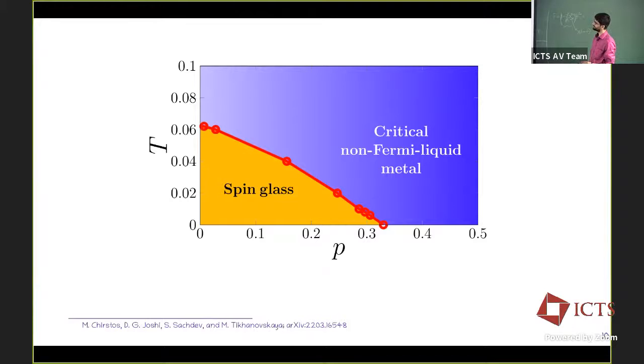and then you obtain such a phase diagram. So all these red dots are the critical values of doping obtained using such a Ginzburg-Landau criterion. So on the right-hand side, at the overdoped region, you have this critical non-Fermi-Liquid metal, and then it has an instability to the spin glass phase at low temperature. So this is the temperature versus doping. And it looks nice in the sense that at least phenomenologically, it looks like the cuprates, where you have at low doping some spin glass, whose order parameter vanishes as you increase doping, and then it goes into this critical non-Fermi-Liquid where you would have T-linear resistivity.